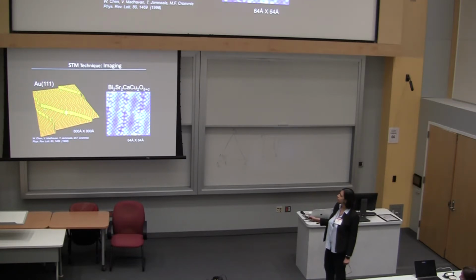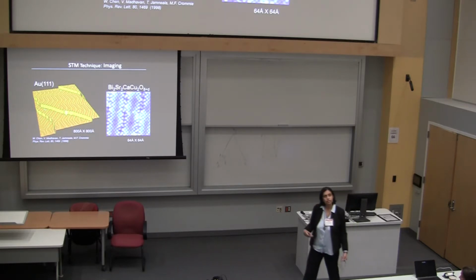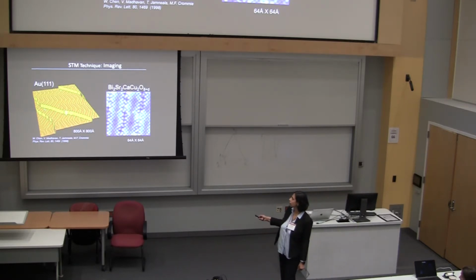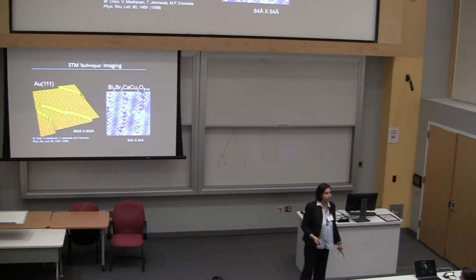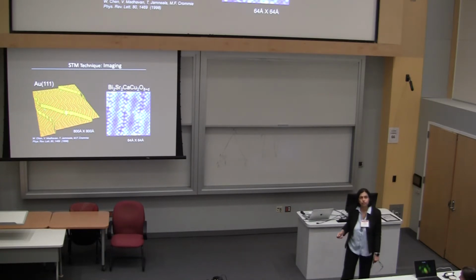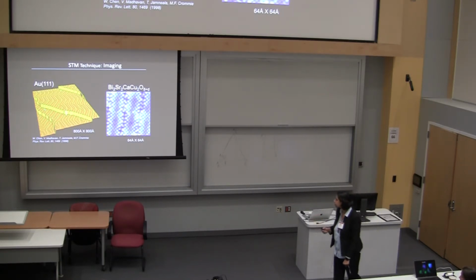And you can also see it has a two-dimensional electron gas on the surface. You can see these lines parallel to the step edges. That's the 2DEG bouncing off of the step edge and interfering, causing an interference pattern. So you can see all this with an STM.